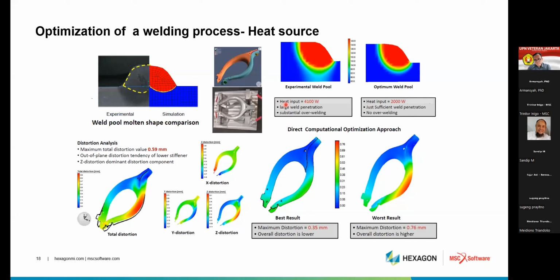Earlier we used a heat input of 4,100 watts. With this heat input, we were getting this kind of weld pool, which had large weld penetration, and substantial overwelding was happening. So then what we did, we reduced the heat input from 4,100 watts to 2,000 watts. With this heat input, we got just sufficient weld penetration and no overwelding was happening. And with the reduction in heat input, the distortion also got reduced.